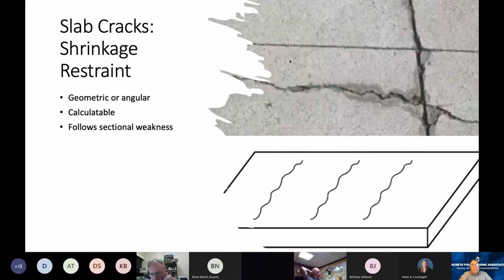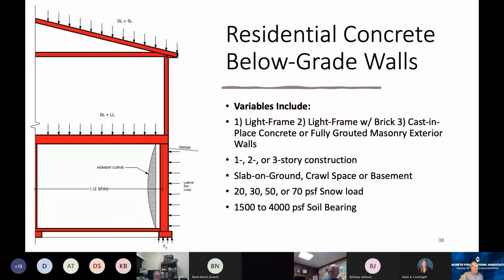Inevitably, concrete, if I look at this particular crack that's starting to warble along here, my opinion is that it started on the right and worked to the left. If it had come from the left working over to this vertical slab joint, and let's say I had a couple number 4s running the length of that slab joint on the inside, on the left side and on the right side, that may have been enough reinforcement to seemingly stop that crack. And so if you're seeing a crack that kind of meanders like that and then stops, two things are going to happen. One, it's going to hit reinforcement to control it, or it hasn't been long enough. And generally speaking, the answer is it hasn't been long enough, and it'll crack through. Great question. Thank you for jumping in and asking that.